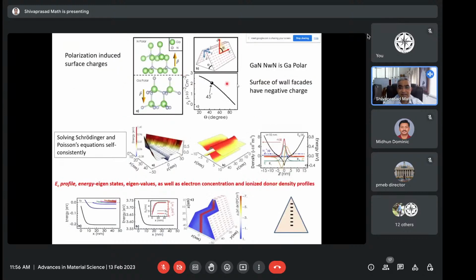Okay, so we again did some calculations to understand what is actually happening in these materials. And then we came out with the theory saying that because of the surface states of these materials, which have dangling bonds, actually those electrons get pushed inside, and you form a two-dimensional electron gas in the middle of these wedges. And so these 2D electrons are protected from outside, right? So we tried to saturate these dangling bonds by putting various gases on top of it, but we could not because these electrons have already been pushed inside.